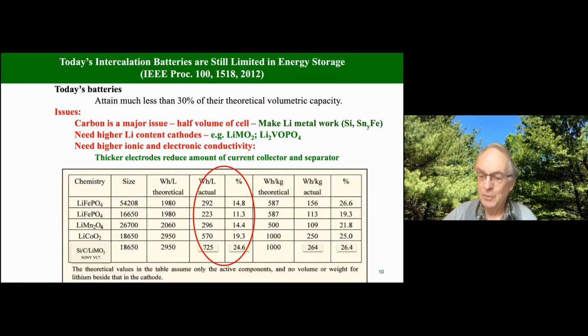I get lots of questions from people. Well, you got the Nobel Prize, so nothing needs doing with lithium ion anymore. And I say, that's not the case. And as Jeff showed, we have many limitations. The real issue is today's lithium-ion batteries store much less than 30% of their theoretical volume capacity and of their weight. And you can see just some numbers in the red circle here. Lithium iron phosphate is between 11 and 14%, and the layered oxide can get as high as 25%.